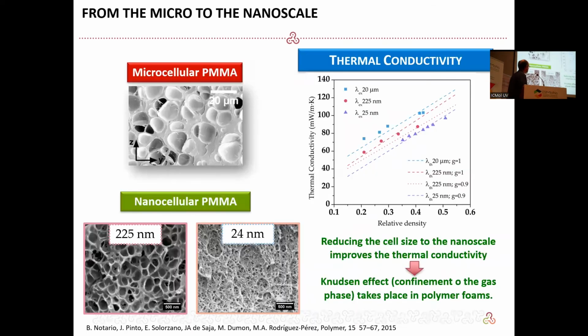Regarding thermal conductivity, that is a very important property because we need thermal insulators for everything, especially today that we want to have low energy consumption in the buildings. So we need to isolate properly the buildings. So thermal conductivity is a very important property for us. And here we are comparing, for instance, some nanocellular polymers produced in our lab. This is a polymer with an average cell size of around 200 nanometers. And this is a polymer with an average cell size of 24 nanometers. And this is a microcellular. All of them produced with the same material, PMMA, polymethyl methacrylate, similar relative density.